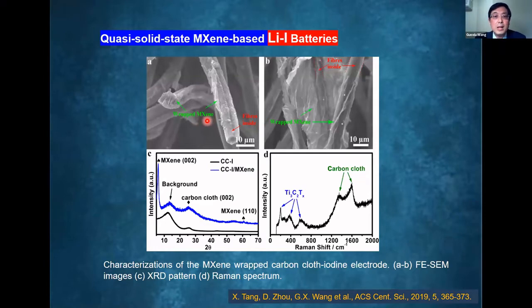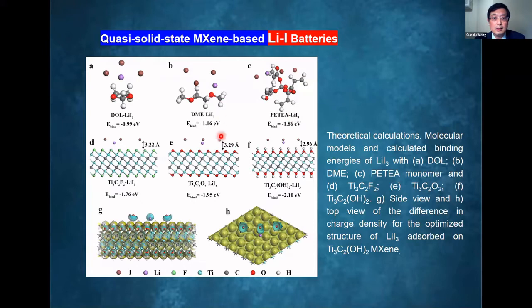We can easily wrap individual MXene nanosheets on individual carbon fibers in carbon cloth. And then we can soak this MXene-wrapped carbon cloth with iodine as a cathode, and then use them as a cathode for lithium iodine batteries. And this is the theoretical calculation. You can see the MXene shows stronger adsorption towards lithium iodine.